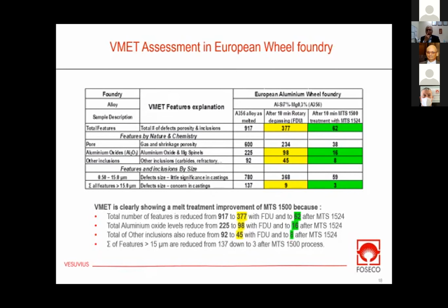More importantly, the last line, features bigger than 15 microns, which are a real concern, those that lead to rejected castings, show a real reduction. This is very nice proof that for people who don't believe in rotary degassing, it not only removes hydrogen but has a direct effect on inclusions and oxide. In the past, especially in high pressure die casting, many people disputed that, didn't believe rotary degassing would impact their melt quality.